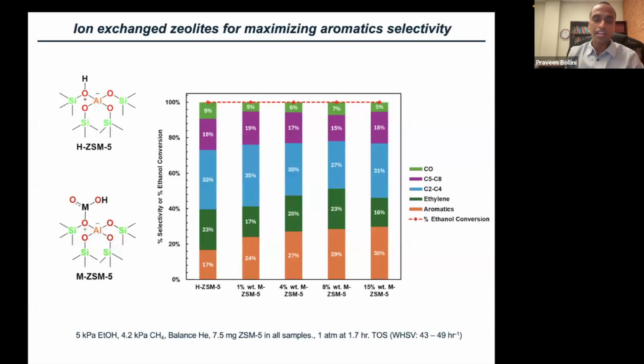In terms of the data itself, what you can see is as I go from left to right and load more of this ion exchanged metal, we're able to shift the selectivity from ethylene over to aromatics. So what the ion exchange process was able to do is shift the selectivity of the products to aromatics to improve the aviation fuel value of the end product while not affecting the catalyst lifetime negatively.